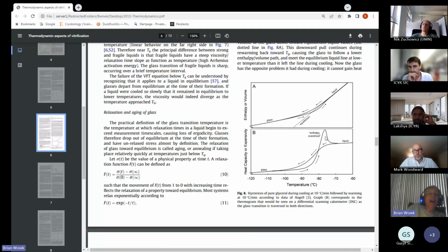actually the main thing that the aging glass is going to affect is thermomechanical stress, because thermomechanical stress will relax on the same time scale as the other glass relaxation that we're talking about. So you'll get a relaxation of thermomechanical stress. In that sense, the aging is actually a good thing. Offhand, I can't think of anything cryobiologically bad about the aging of glass. In a minute, we'll talk about ice nucleation, but that's completely different. That's unrelated to the subject of glass aging.